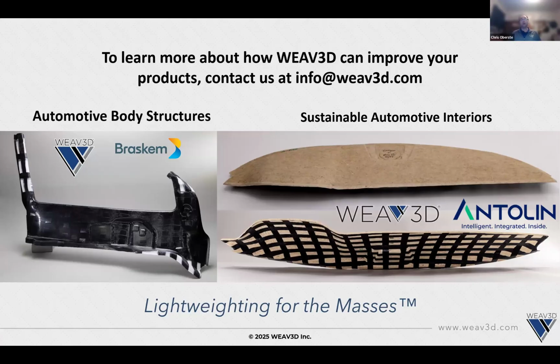This is actually something that we're hoping to be presenting at the member meeting in June. We've been doing a project with another IACMI member looking at deep draw of a different type of natural fiber nonwoven. In that use case, we were able to get about 4 inches, maybe a little bit more than 4 inches, of depth of draw. Even though the lattice itself does not stretch, the openings between the tapes mean they can change their angle. So you get some relief of the forming behavior through angle opening of the tapes. They don't stay 0-90.